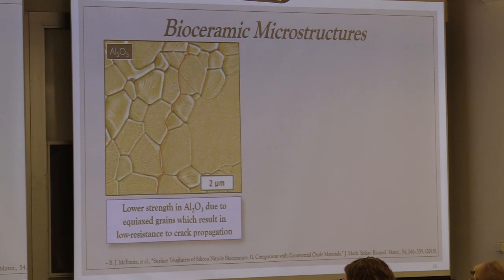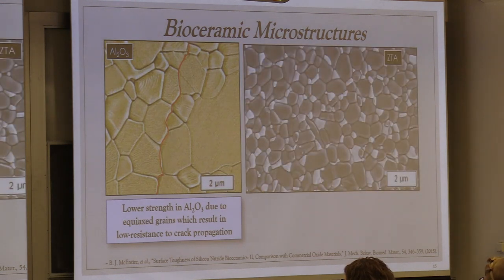It has lower strength because of the equiax grains, and it has a low resistance to crack propagation. So they came along with zirconia and zirconia-toughened alumina, which is this microstructure here. Now the dark phase in here is alumina. The lighter phase here is zirconia, but there's also a strontium aluminate phase in here, which is actually a fibrous type structure, kind of right there, which in this particular material was engineered by Ceramtech in Germany.